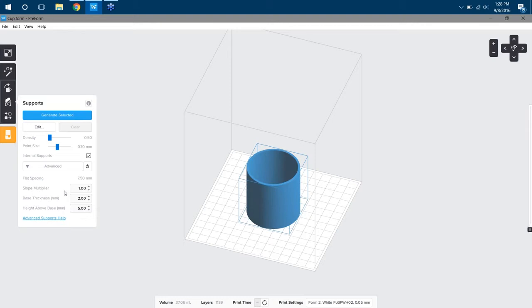But below that, we have base thickness. This is actually pretty useful if you have trouble with non-adherence. You can increase the strength, the depth of the base. That will increase the bond, but make it harder to remove. If you decrease the strength, it'll make it easier to remove, but you might end up with some wobble on your part during the print operation. And then finally, height above base. That's pretty self-explanatory. That's how high the part is above the base itself.